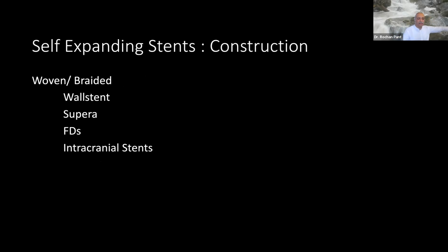Now, these are examples of woven braided self-expanding stents. The Wallstent is the premier example, and anybody who uses the Wallstent will tell you, the problem with braided stents is the final length of the stent depends on the diameter you allow it to expand. Supposing you put a 10 millimeter stent into an 8 millimeter vessel, it's not a problem, but the stent will become longer. So if you have a vessel with varying dimensions, then the stent accommodates it very well, but the final dimension of the stent is hard to tell until you have actually deployed it.